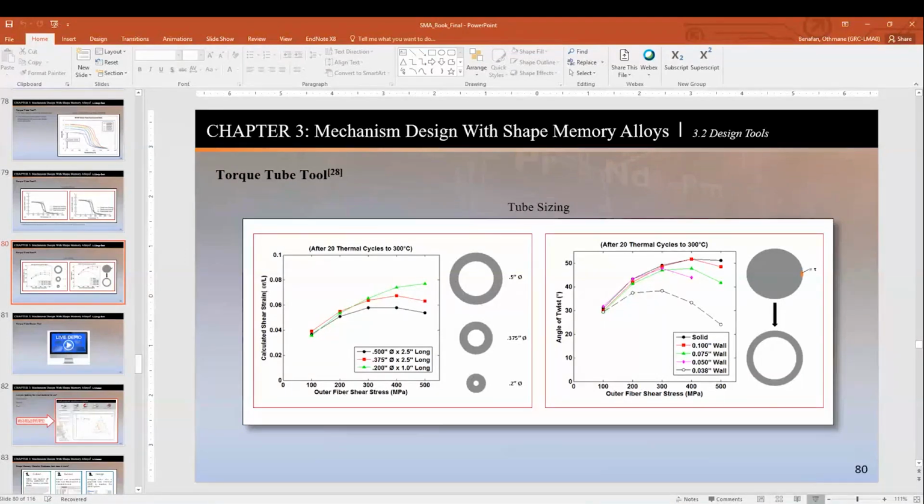So there's some profile that looks like this, okay, in conventional metals. The stress in the metal is 0. As you go out to the outer shell, the stress is maximal. In the SMA, frankly, we don't even know what it looks like. Maybe like this, or I have no clue what that stress distribution looks like. But if I have a solid of this form or that form, you can see here they are all the same, in the normalized fashion.